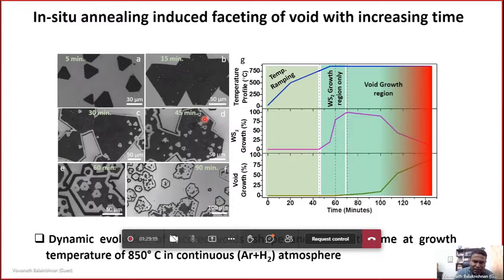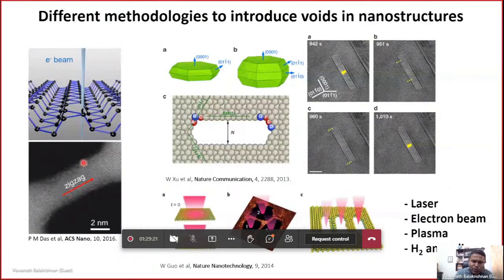The literature that I have shown, what they have done is they have used TEM. If I take your question, can we use the electron beam that we use for lithography to produce defects? The answer is yes, but it depends upon your voltage. Typically, for graphene, in order to remove the carbon atoms, we need somewhere around 80 kilovolts. For 2D materials, I need to check what the exact number required is.